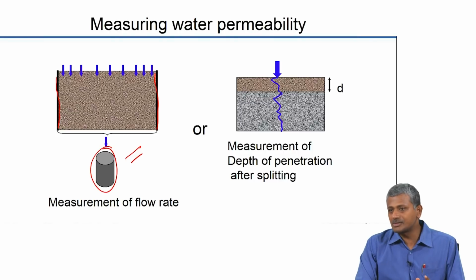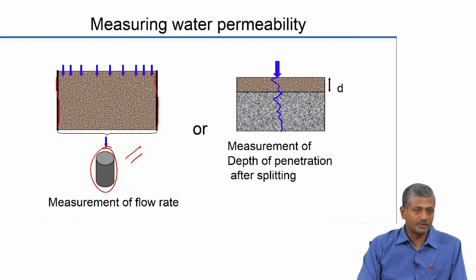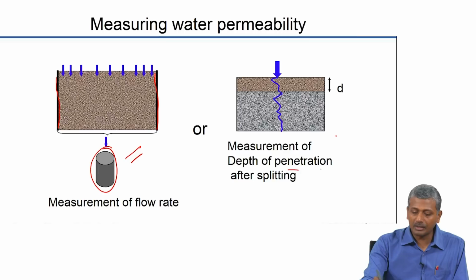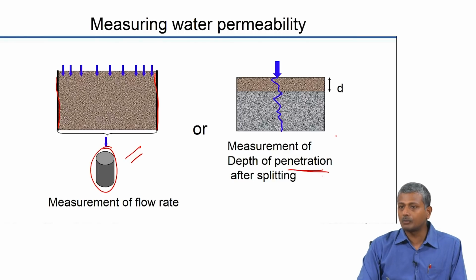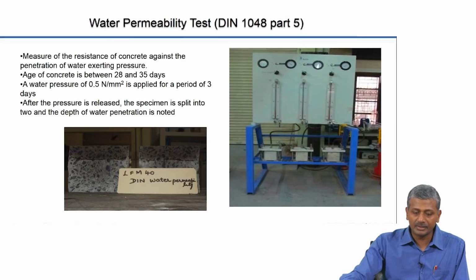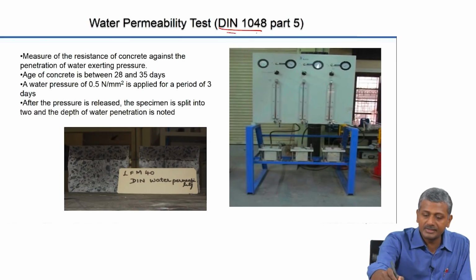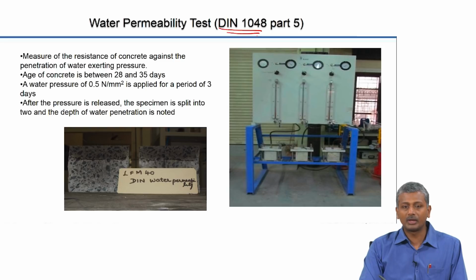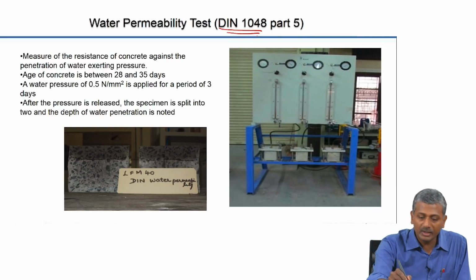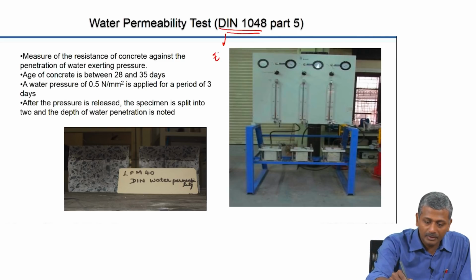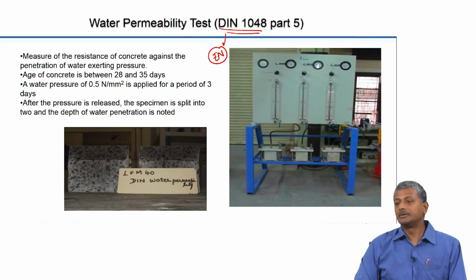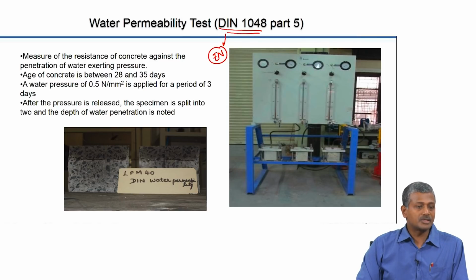So this test is not easy, and nobody seems to be using this test nowadays. Okay? What people prefer is the water penetration test. So we can't call it a water permeability test anymore, we call it the water penetration test under pressure. And this has been standardized by the German standards, DIN 1048. Now of course this is also now an EN standard. I'm sorry, I don't have the EN number for this. It was originally a German standard, but now it's an EN standard.